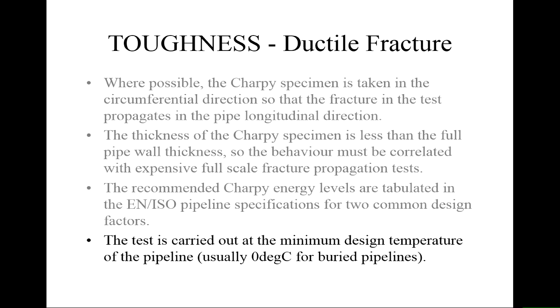The other thing that you need to bear in mind, of course, is that these steels undergo a ductile brittle transition, and when you change the composition of the steel, you change the temperature at which there's a transition between ductile and brittle. So if you just specify a Charpy energy, you've got to be careful that that applies at the lowest design temperature for your particular asset.